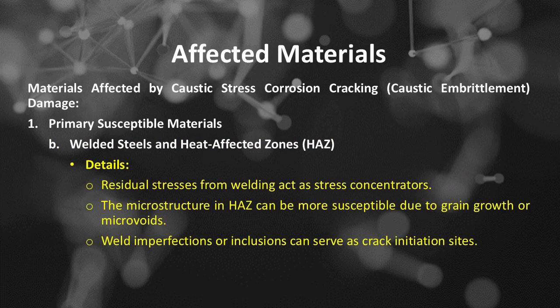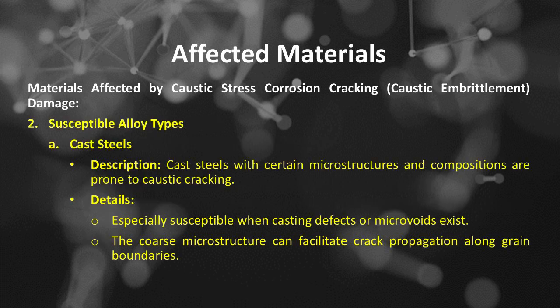Here's detail of welded steels and heat-affected zones affected by CSCC. Residual stresses from welding act as stress concentrators. The microstructure in the HAZ can be more susceptible due to grain growth or microvoids. Weld imperfections or inclusions can serve as crack initiation sites. Number 2 of materials affected by caustic stress corrosion cracking or caustic embrittlement damage is susceptible alloy types, which includes: Number A, cast steels with certain microstructures and compositions are prone to caustic cracking.